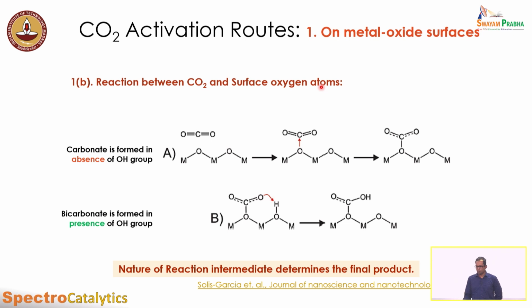This is a simple metal oxide, nothing but metal-oxygen bonds and terminal metal and oxygen atoms on the surface. So what happens is CO2 comes in a bent configuration, and oxygen attacks the carbon of the CO2 molecule, and we form a monodentate carbonate type of species here.